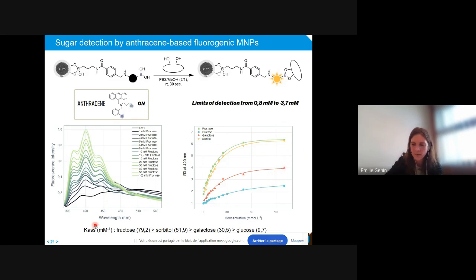We were also able to calculate the association constants, and here you can see that the affinity is higher for fructose than galactose and glucose, which is the classical order observed in solution. In terms of limits of detection, they are between 0.8 and 3.7 millimolar, which is relevant regarding the concentration for diabetes or even healthy patients.